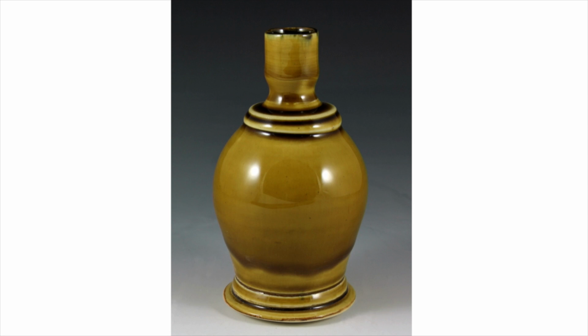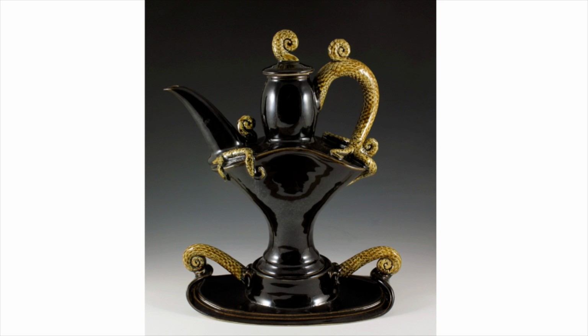And then, since the glaze reveals texture so wonderfully, the way it breaks over an edge and pools in depressions, I used it to glaze one of my teapots over the textured handles. So this is fired to cone 6 in an electric kiln.